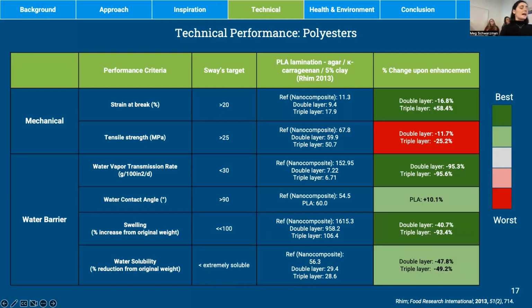So for our polyester strategy, we're focusing on PLA as a coating to act as a protective barrier for the films. The study that we present in this table looked at how PLA lamination could enhance the properties of their nanocomposite films, which consist of agar, carrageenan, and 5% nano clay. In this study, they also use the casting technique to form the films. They have a double layer, which is just the nanocomposite film coated on one side with the PLA, and then the triple layer film is referring to the nanocomposite film coated on both sides with the PLA. And hydrogen bonding is what is allowing these layers to stick together.